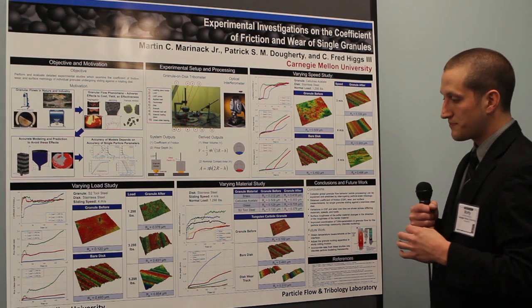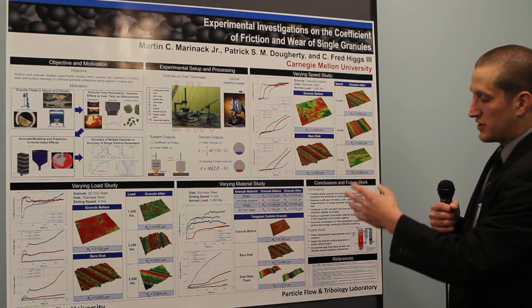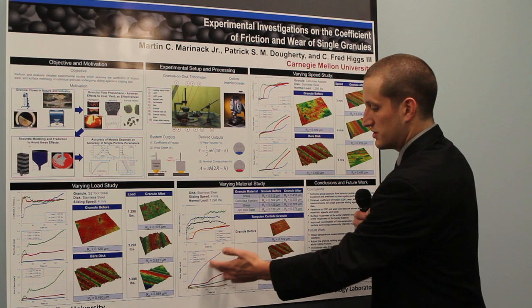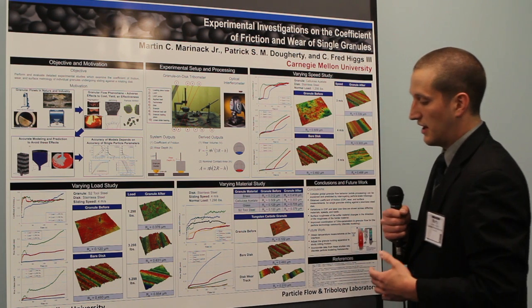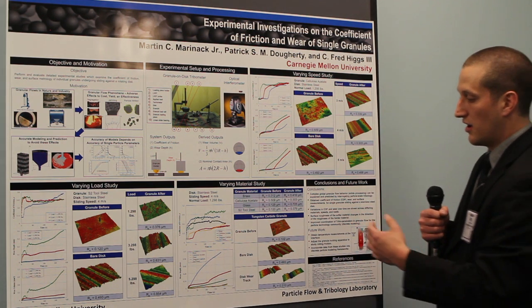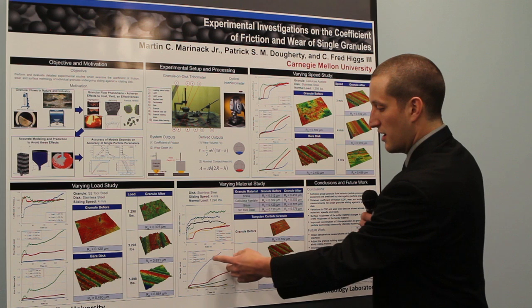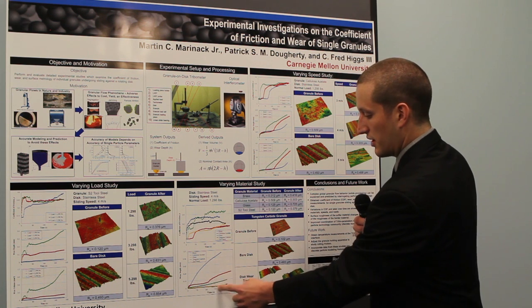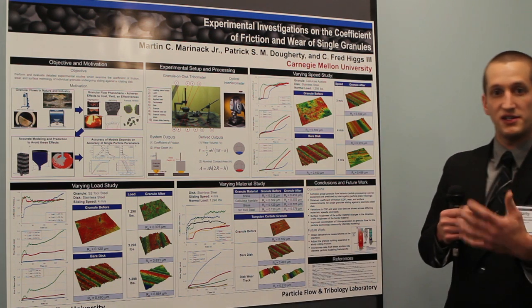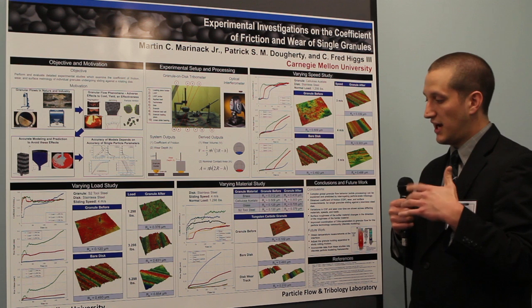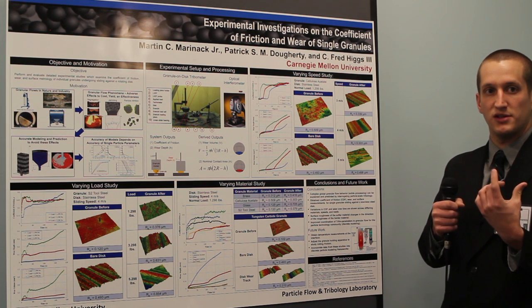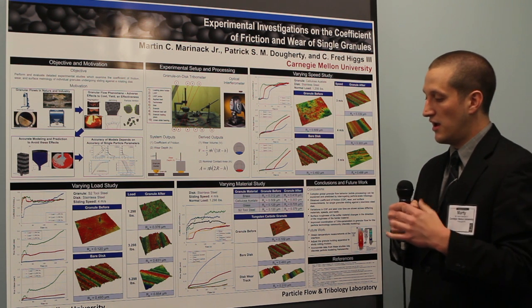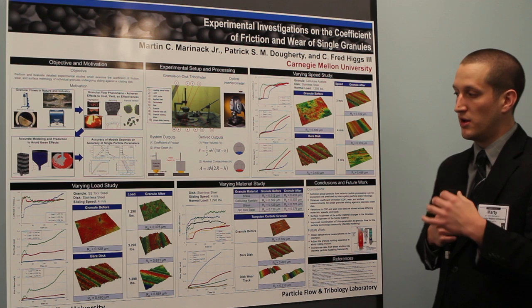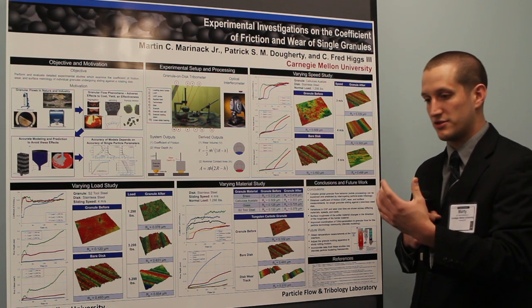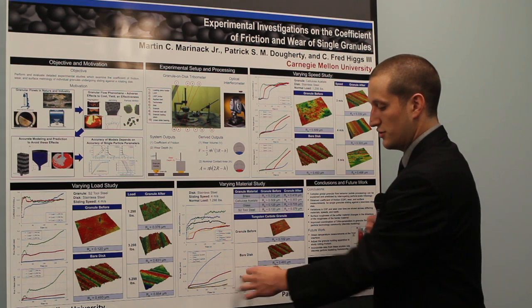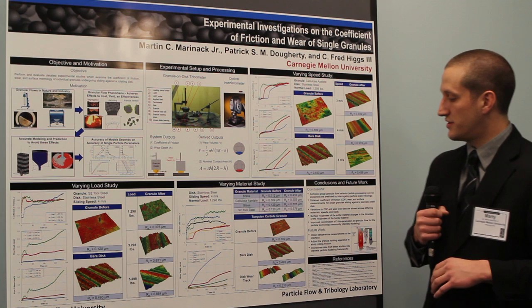In terms of the friction and wear plots, we see that brass, which is the softest material, provides the highest amount of wear, which isn't surprising. One interesting thing to note is that the tungsten carbide and the tool steel granules are showing the same wear depth, and this is not surprising because in the case of the tool steel granule, the granule wears, and so we have steel material wearing. And in the case of the tungsten carbide granule, the disc actually wears, which is also steel. So it's not surprising that these two tests fall on top of each other.